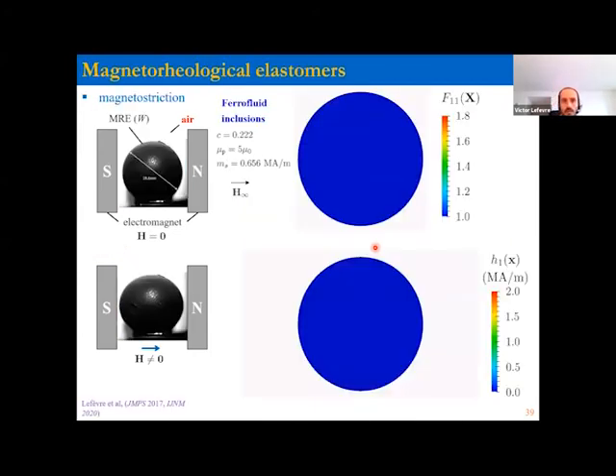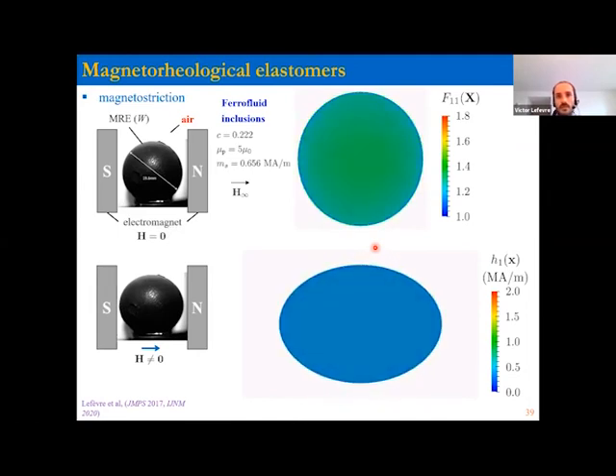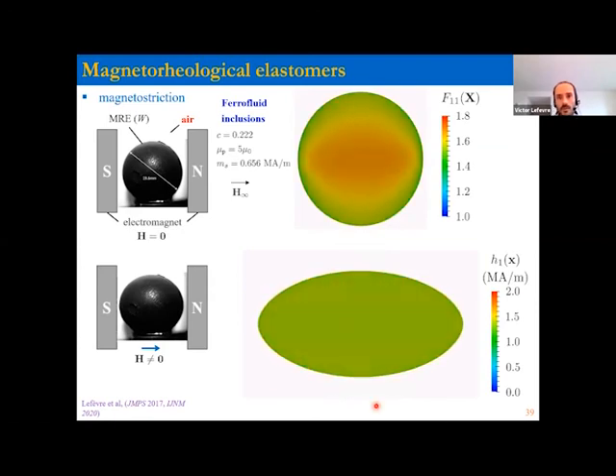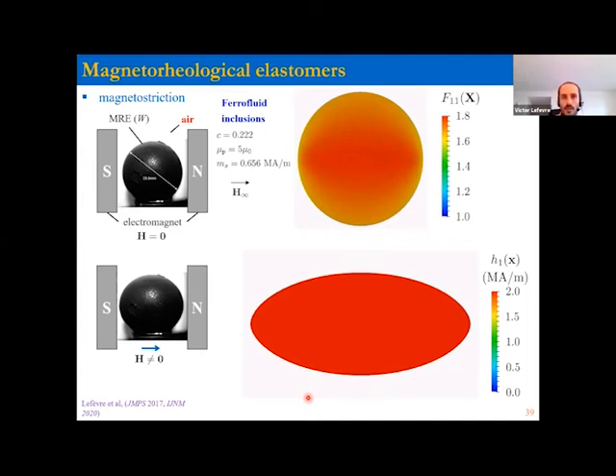What you can also do is look at ferrofluid inclusions. That's something that we've proposed because these iron particles, yes, they make the material responsive to magnetic fields, but they're very stiff. So they increase the stiffness of the composite. With ferrofluids, because the ferrofluids are soft, you make the composite actually much softer, and you can see that you can induce much larger deformations when you have ferrofluid inclusions. This is something that we've proposed based on this theoretical modeling, has yet to be explored experimentally, but that's something we're excited about.